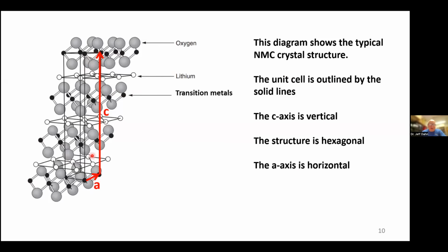Well, if you go and look at the atomic structure of an NMC material, you can see here the transition metal atoms shown in solid black, the oxygen atoms shown larger in gray, and the lithium atoms shown in white. And as the lithium is removed and reinserted into the structure, these vectors called A and C change in length. These are the characteristic vectors that describe the crystal structure. It just repeats again and again and again. But the distances between these neighboring transition metal atoms and the distance between the layers changes as the lithium content changes back and forth.